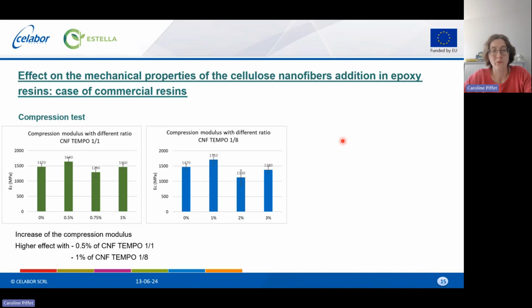Those resins were reproduced to have confirmation of the result, of course, but also to have sufficient samples for characterization of the mechanical properties. And we performed compression tests, and so saw the compression modulus with different ratio of nanofibers, the 1,1 and the 1/8 that were selected.